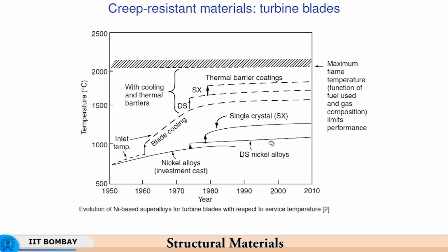So, that is the reason why it is important to have micro channels in these turbine blades. And you see the evolution of these technologies over a number of years. Earlier, people were using not exactly single crystal, but investment cast or conventionally cast nickel alloys, and they were relying more on blade cooling to prevent creep, whereas subsequently these technologies were available, plus an additional factor of being able to control grain size came into play until 2010, and therefore the life of the turbine blades increased enormously.